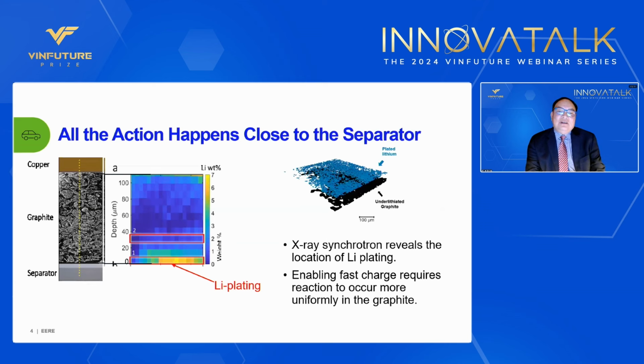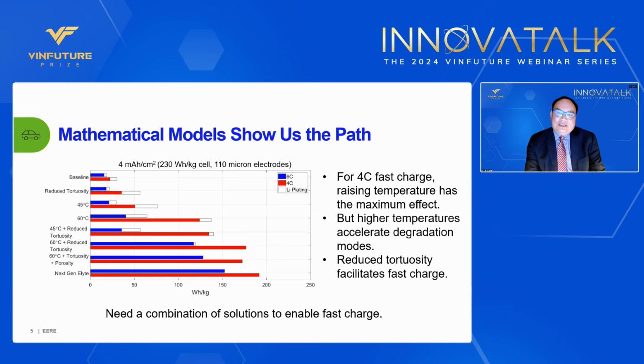Now, this slide tells you clearly through X-ray synchrotron that most of the lithium plating is at the separator side. You can see clearly the yellow area, that's where the lithium plating is. So one of the goals to enable fast charge is to require the reaction to occur more uniformly in the graphite, not plating lithium at the area between the separator and the graphite. So how do we do this? We do this in a program by doing mathematical models.